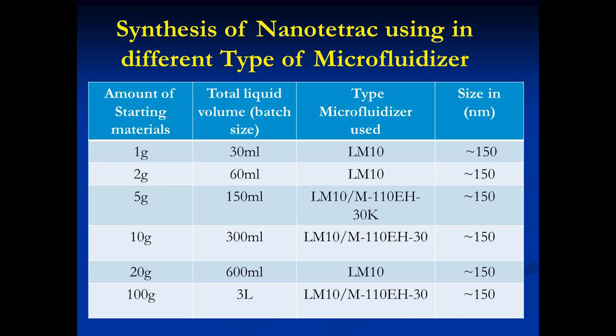in the LM10 microfluidizer. And at the same time, if we use 100 grams of our starting material in 3 liters, and even if we use either the LM10 or the M-110EH-30 microfluidizer, still we get the same kind of nanoparticles we are looking for. So my recommendation would be that you can get exactly the same size nanoparticles using different kinds of microfluidizers, and even different amounts of volume or material. So it's not a factor in this case for synthesizing the nanoparticles.